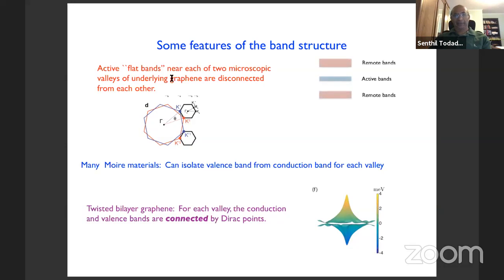Now, each one of these active flat bands, if you remember the electronic structure of graphene, there are two valleys in graphene corresponding to the two corners of the hexagonal Brillouin zone. Now, corresponding to each one of those two corners, there's a separate valley that's inherited by all of these Moiré structures. And the active bands near each of these two microscopic valleys of the underlying graphene are disconnected from each other, right? So the Moiré lattice spacing is so much bigger than the graphene lattice spacing that the momentum associated with the size of this mini Brillouin zone is small compared to the size of the big Brillouin zone, and therefore compared to the separation between the two valleys.